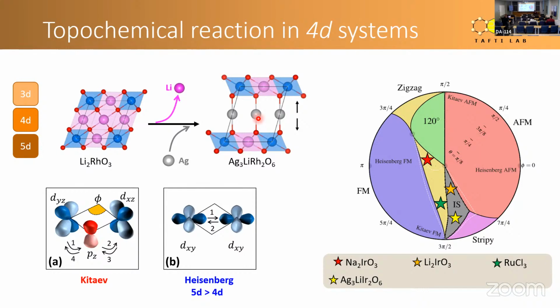Again, there's a sort of heuristic chemical intuition for that. As I explained previously, the Kitaev interaction is predominantly a superexchange interaction, whereas the Heisenberg interaction, which is responsible for magnetic ordering, is predominantly a direct exchange interaction. Now, when you go from 5D to 4D, both interactions become weaker because the spatial extension of 4D orbitals is less than 5D orbitals. But it so happens that the direct exchange interaction weakens faster than the Kitaev exchange, than the indirect exchange interaction.